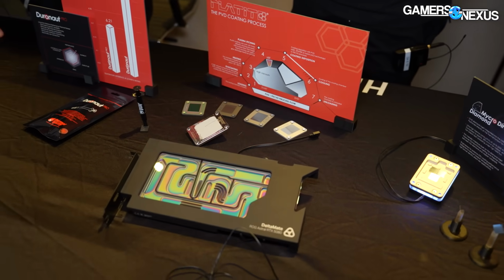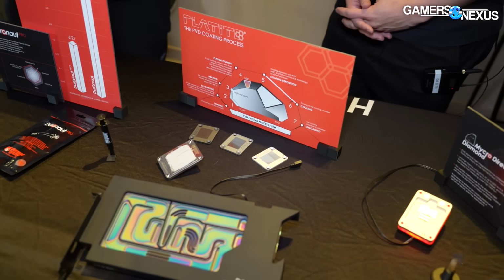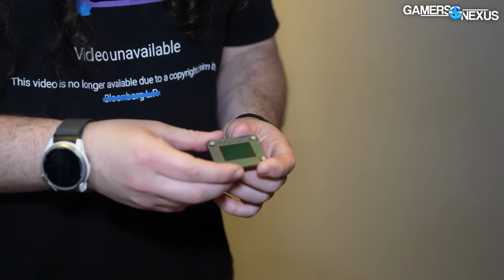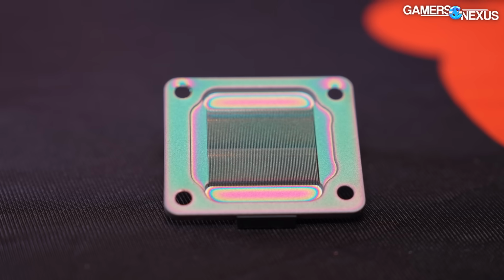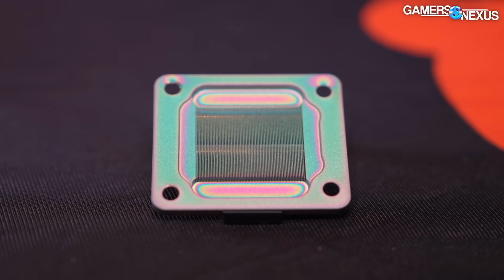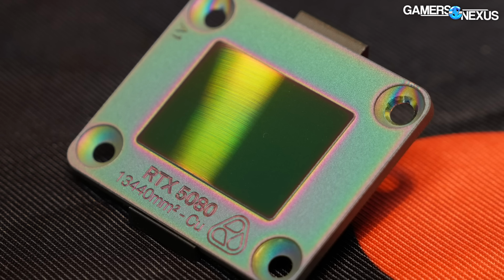We want to move away from nickel plating as much as we can. These are better in all aspects, from a corrosion perspective and especially from the thermal performance. This is a dual layer thing, so there's a metal layer underneath and then an oxide layer on top. This oxide layer is very thin, and that's what's causing the different colors.